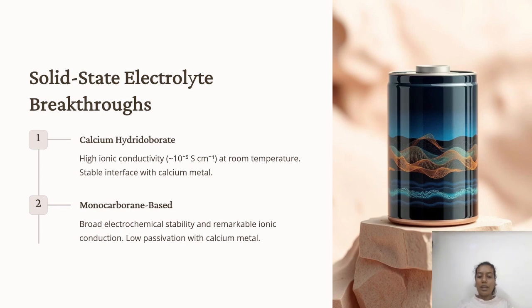The second major breakthrough is the monocarborane based solid electrolyte, namely calcium monocarborane. This material has a unique cage like molecular structure that enables excellent ionic mobility while maintaining a stable interface with the calcium metal. Importantly, it resists forming the thick passivation layers that hinder performance in most other systems. Both these materials offer new hope in addressing the long-standing issue of poor interface compatibility and low ionic mobility in solid-state calcium batteries.